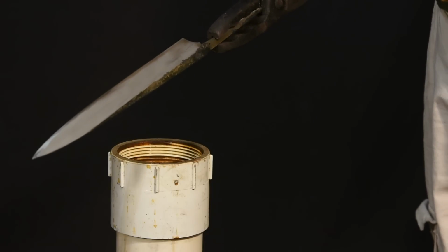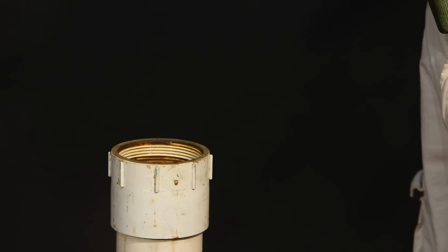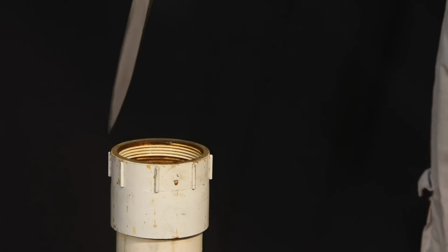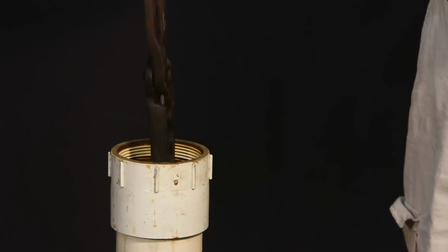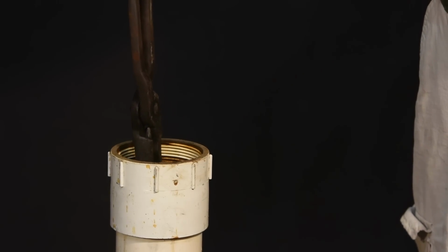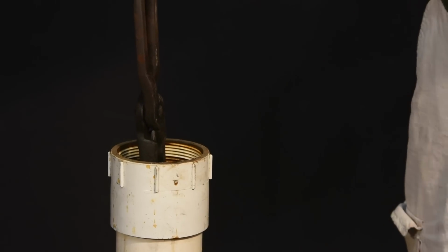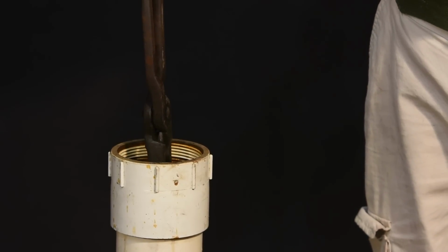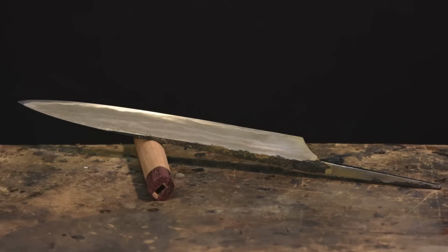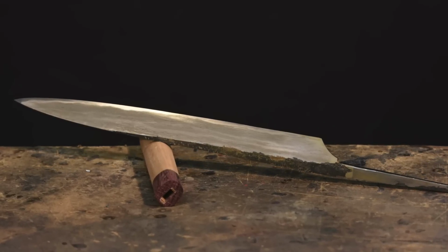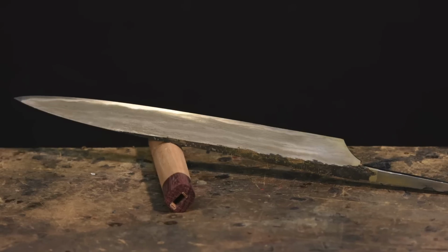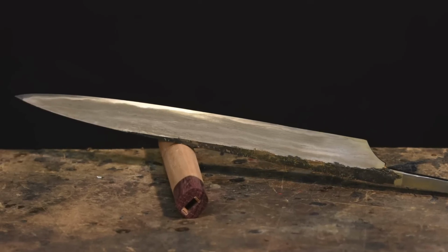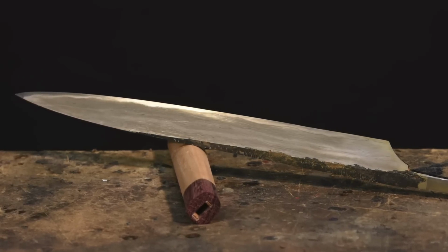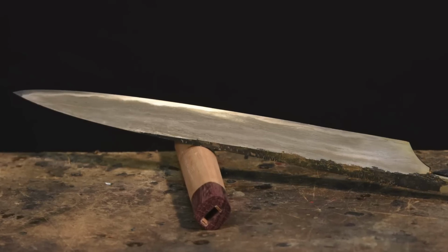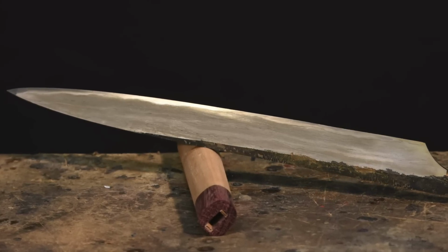So finally, I'll etch the blade in a very dilute solution of ferric chloride to expose the grain of the iron. If you do this with a relatively porous material like wrought iron, make sure you neutralize it with a base. In this case, I'm using baking soda, but there are other things like TSP that you can use. Otherwise, tiny amounts of the etchant will sit inside all those tiny little crevices and just rust the crap out of your knife over time.